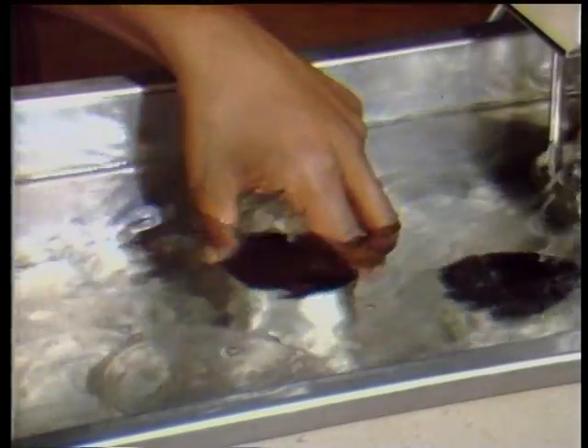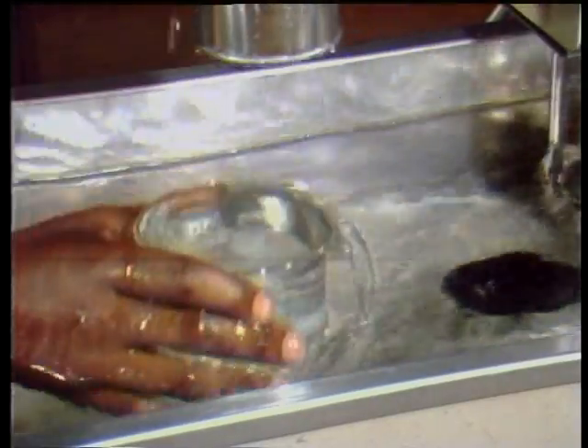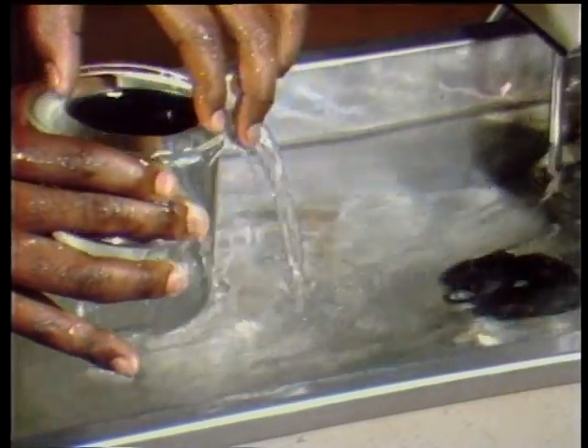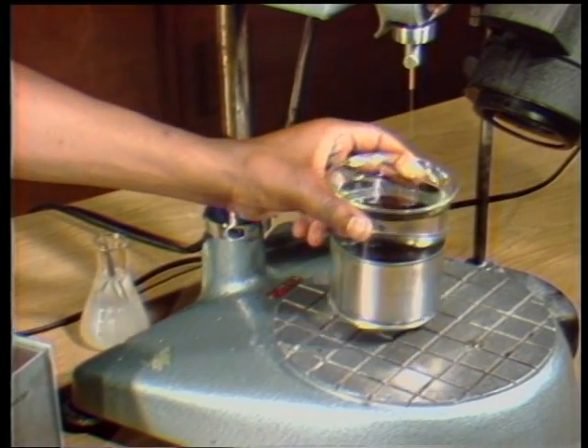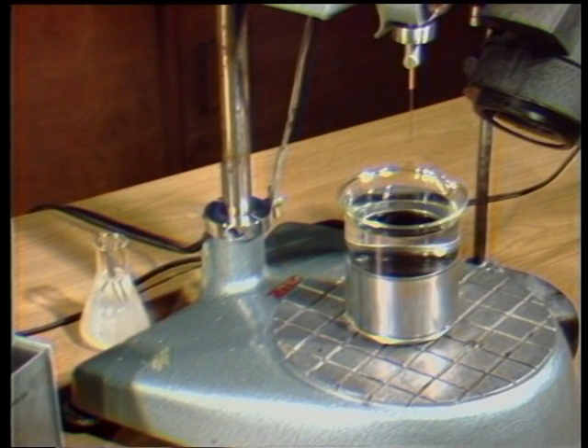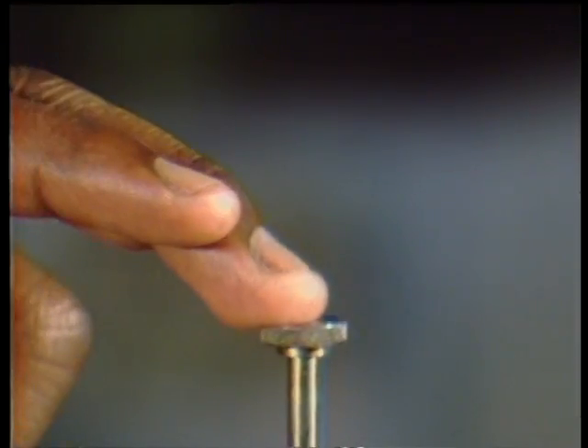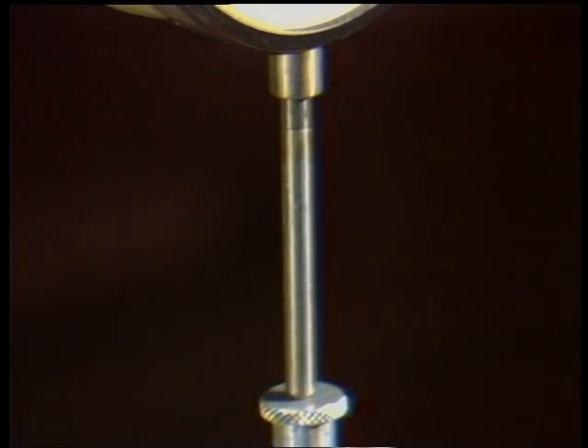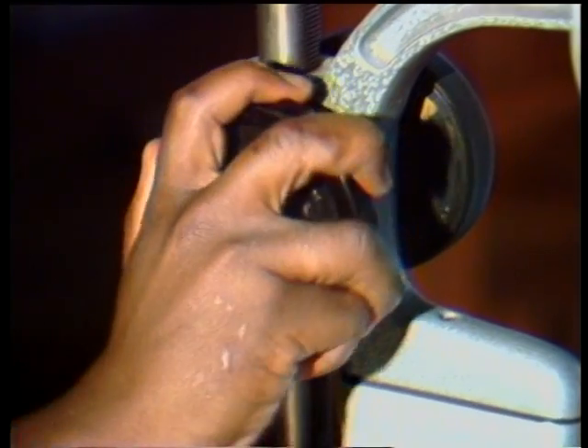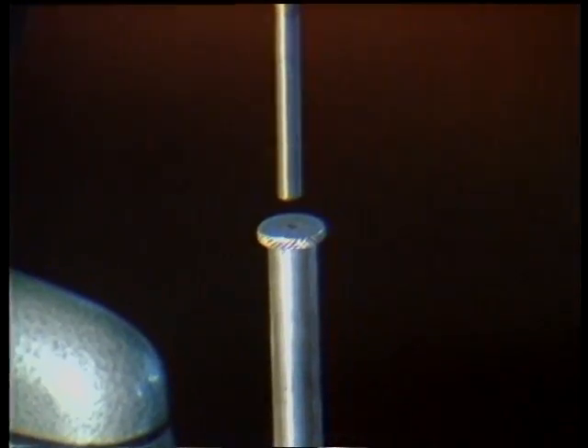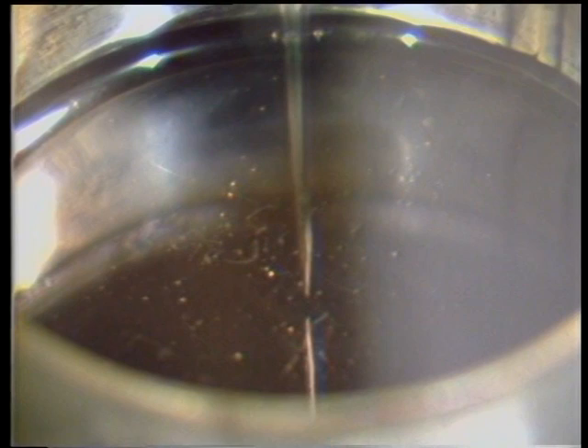Method. Remove the specimen from the water bath after an hour and a half and place it in a transfer dish that has also been in the water bath for 1.5 hours. Cover the specimen completely with water from the water bath. Place the transfer dish and the specimen on the penetrometer stand. Zero the penetrometer. Slowly lower the needle until it just makes contact with its image as reflected in the bitumen surface.